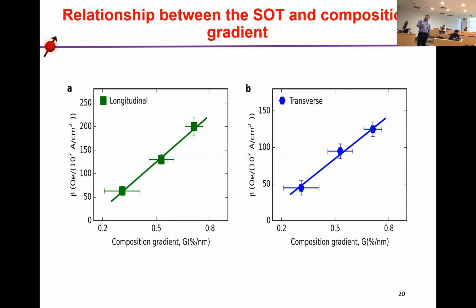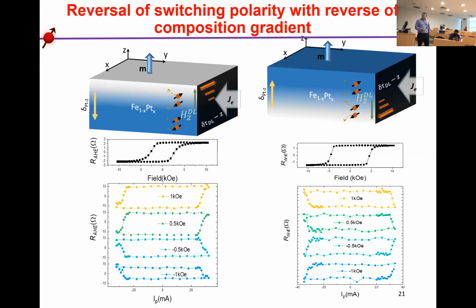We have also studied how this SOT effective field relates to the composition gradient. It increases with the composition gradient. And we have done another experiment that further confirms this SOT originates from the composition gradient. We reverse the gradient. For example, the first one has platinum increasing along the Z direction, and the second one has platinum decreasing along the Z direction. Both show perpendicular anisotropy, but the switching polarity has reversed. This further confirms that the switching is due to the composition gradient.